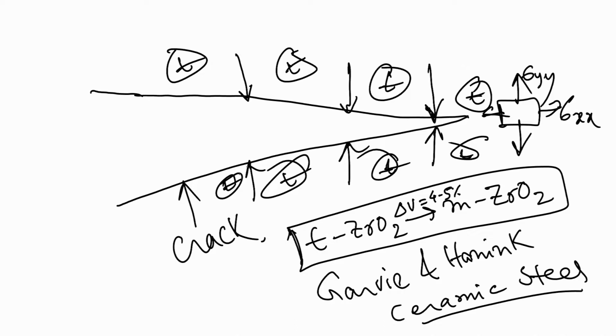This crack opening displacement, that is called COD, crack opening displacement. So, this crack opening displacement is reduced, and therefore, the crack tip will be blunted. So, from this very basic information on how tetragonal zirconia can influence the crack growth resistance in the microstructure, it should be clear to the students that this tetragonal to monoclinic zirconia transformation can be invoked at the crack tip, and that will lead to the crack tip closure or crack tip blunting, that will lead to the increase in the crack growth resistance, ultimately K1C, that mode 1 critical crack tip fracture toughness also would increase.